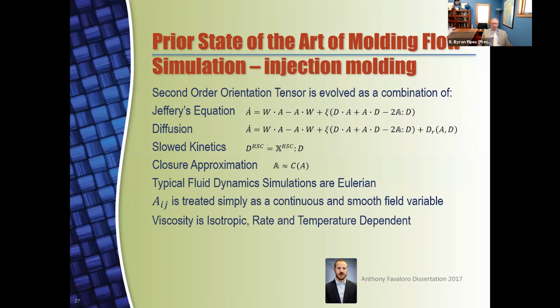That diffusion term stopped the rotational behavior as if we're interacting with other fibers with this diffusion term. It gave us slowed kinetics. The closure approximation was used to predict the fourth order tensor with a second order orientation tensor, and we have adopted a second order orientation tensor frankly as a basis of this work.